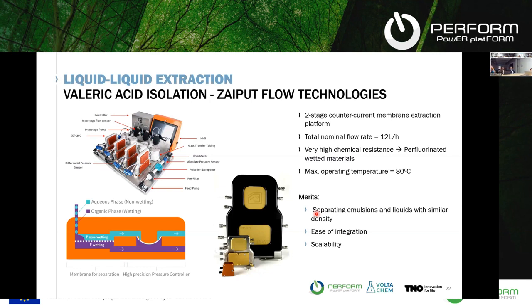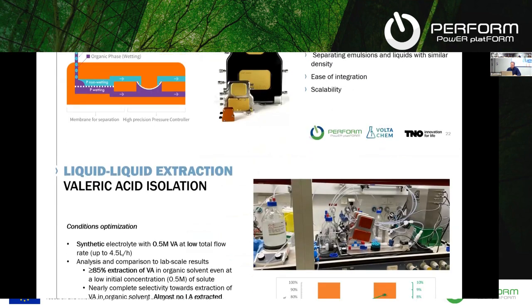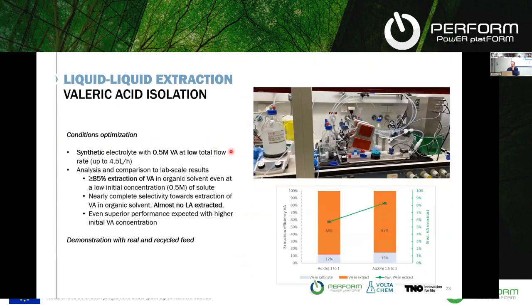The valeric acid has more affinity to the organic solvent, and it will go into the organic phase. But then you need to separate the organic phase that is rich in valeric acid from the water phase that is now richer in levulinic acid, for example, that is your unreacted material. With this, we did some preliminary tests with a mock solution using about half a molar valeric acid, which is more or less the solubility limit of valeric acid.